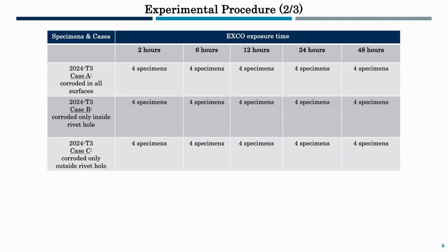The experimental procedure consisted of three different cases. The first case, case A, included specimens which were corroded in all surfaces, both inside the rivet hole and in the surfaces outside of the rivet hole, the upper and down surface of the specimen. Case B included specimens which were corroded only inside the rivet hole, and case C included specimens corroded only in the layers outside of the rivet hole. And several hours exposure to the EXCO solution were selected.